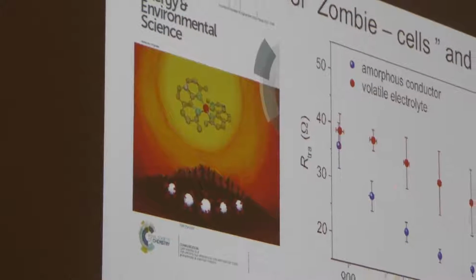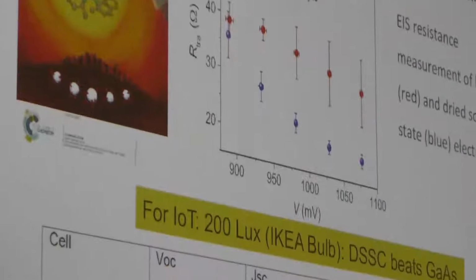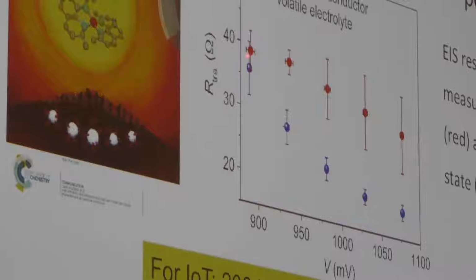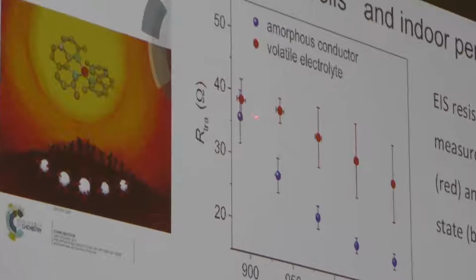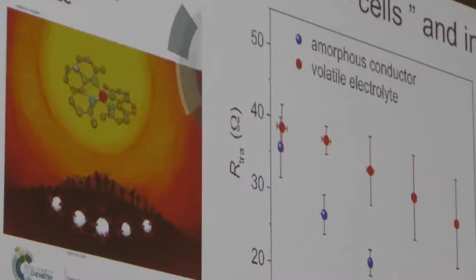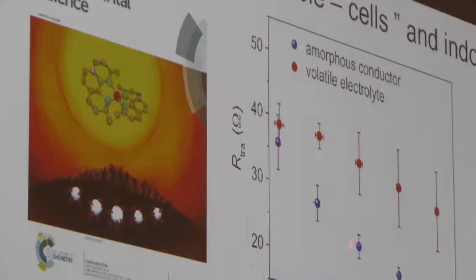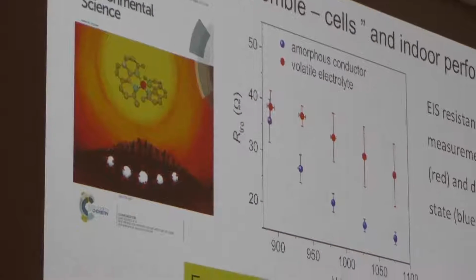This is a conductivity test in the liquid state. That's the red ones. The resistance is higher, and you see the conductivity increases when we go to the zombie stage when it's dried out. So it's some change of also transport mechanism.